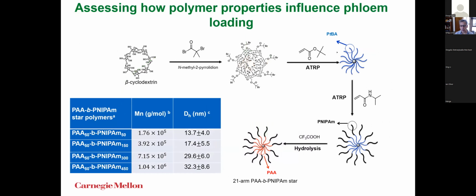That's just two particle types. We started wanting to play around with how the properties of these things affect where they go in the plants. So Elin, I guess I should say, Elin made these polymers. We use this beta cyclodextrin and we do ATRP and grow a bunch of polymer arms off of it. And we end up making a core shell particle with a PAA core, which is negatively charged, and you can load something in it. In this case, we load gadolinium so we can go find it. And then you can have whatever shell that you want.